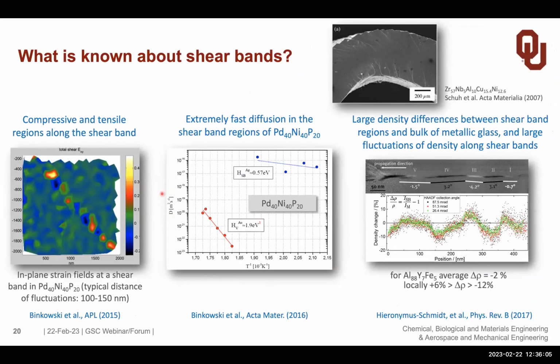So the shear bands are an interesting part of an amorphous structure because it's where the deformation occurs. But the deformation occurs at a very high speed. It's catastrophic, but you can analyze the shear band after you have seen it, and people have done it. So for example, using electron microscopy, like here on the left side, you can see that we have compressive and tensile regions along the shear band.